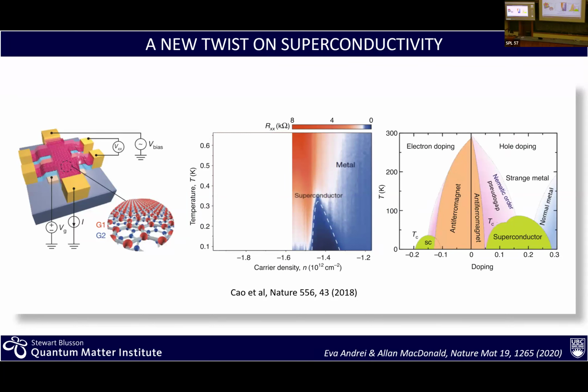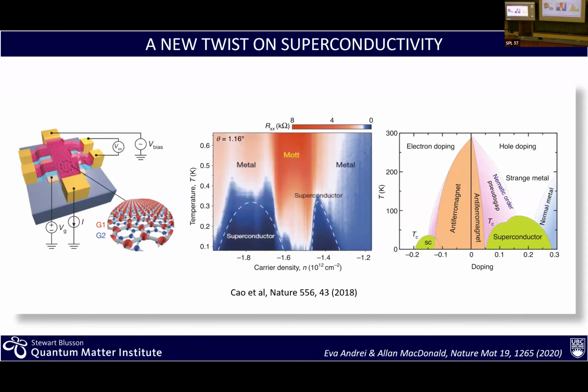And what is really remarkable is if you do the same on graphene, and if you dope now at lower carrier densities, you see again superconductivity, basically two superconducting domes, like here, separated by a Mott or correlated insulator. So that's really where the two systems, even though they live at very different temperature scales, 100 Kelvin, 1 Kelvin, they behave very similar. And this is really having to do with interactions, very strong interaction in the case of the cuprates, and here interactions have become remarkable once you engineer the band structure.